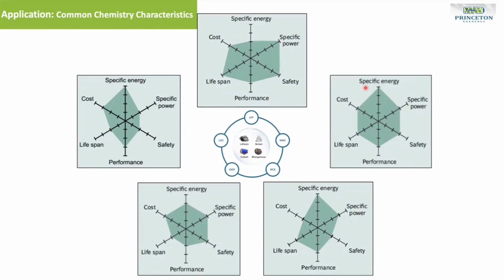So NCA, this one is also for electric vehicles. The difference from NCM is that this is a little bit cheaper, because the aluminum is a little bit cheaper. And also for this NCA material, the ratio is already defined: the nickel content is 85%. The cobalt is roughly a few percent. So that's why it's cheaper than NCM, where nickel is right now 60%. This material is particularly used by Tesla. So you can see most of the high performance cars use these materials.